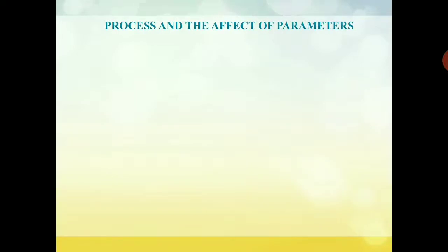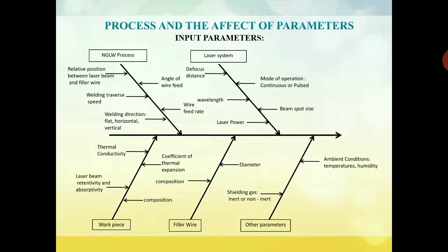NGLW comprises 4 basic steps. First is the designing of the groove, second is the machining, third is autogenous root weld, and lastly it is the welding of the remaining depth with laser and filler. The following fishbone diagram depicts the input parameters that govern the weld. It is important to maintain near identical chemical composition of the filler to avoid difficulties during welding.